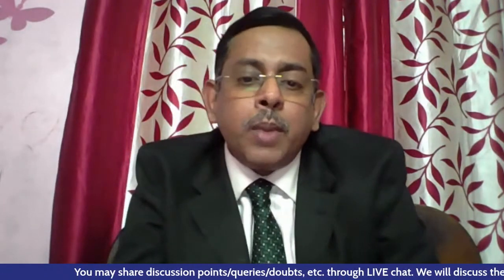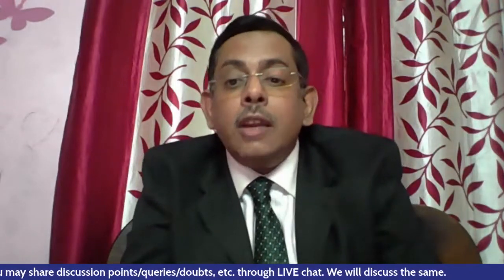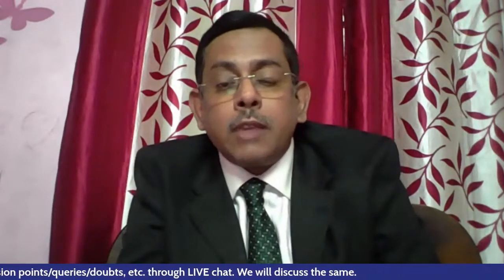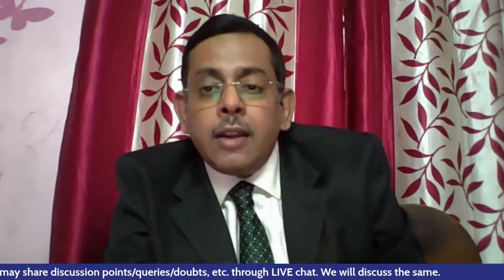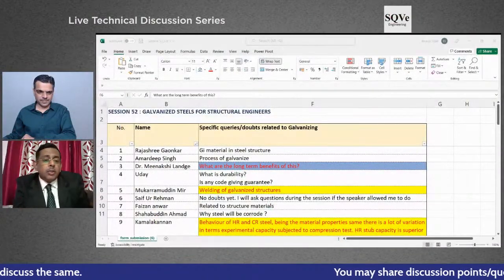Galvanizing increases your corrosion life of the steel surface a bit. Not a bit, it's significantly. 2 to 3 times or sometimes 4 times also. Also, it increases the luster of the steel surface. Your aesthetic approach is also there, because the galvanized surface is lustrous. It will improve your aesthetic point of view beside your corrosion protection. But mainly, galvanizing increases the corrosion protection manifold. I think that answers the questions properly.